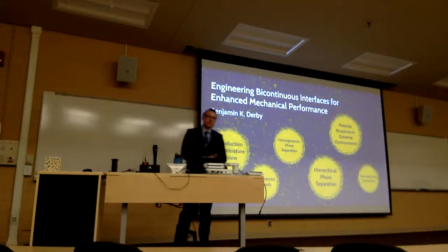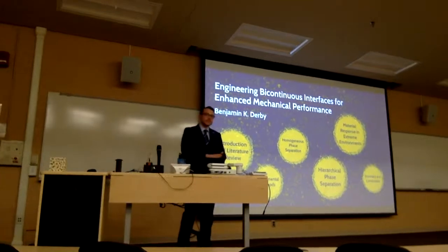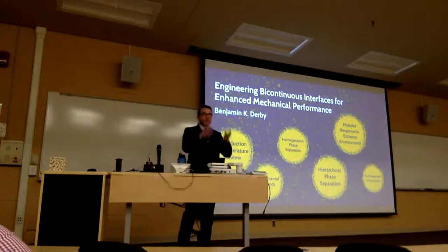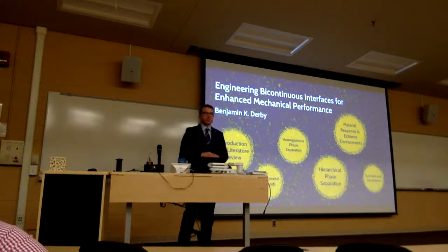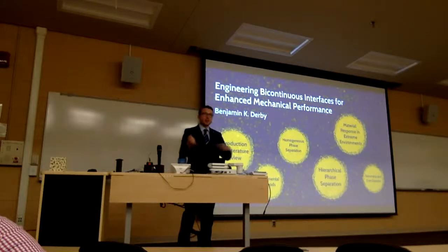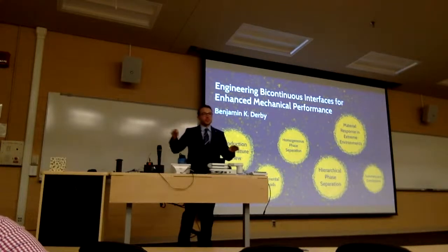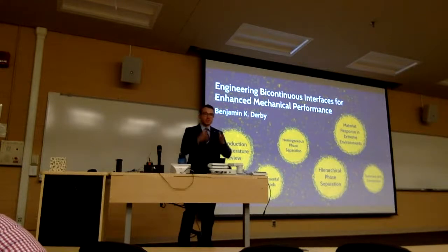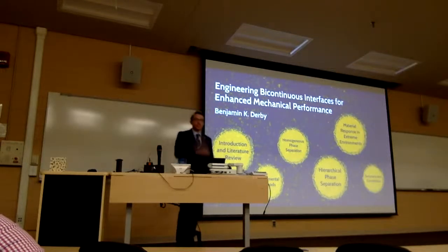For the mechanical deformation of the three morphologies, LCM, VCM, and RCM, why do you think the RCM had lower true stress in comparison to the other two? That's a great question. The LCM morphology actually had kink banding form during deformation, because of the lateral domains of the sample, which behave very similarly to multilayers. We formed some kink bands in that structure in previous experiments. Because these interfaces are now bicontinuous, they have a much more uniform deformation under compression. I think just the design of the domains contributed to that.